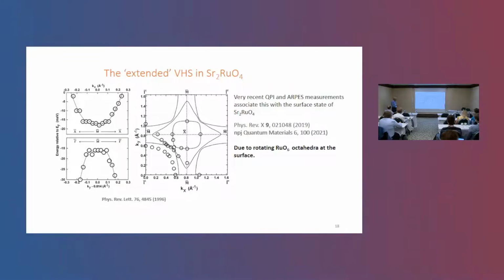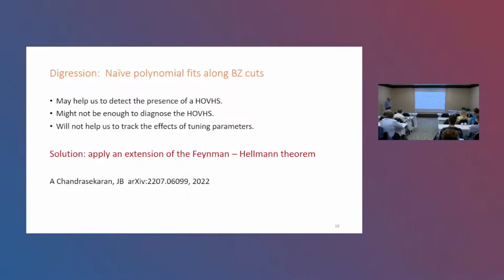People now, especially groups in St. Andrews, did two different classes of experiment, quasi-particle interference experiment and ARPES measurement, and understood that what is extended is a surface state of 214 due to rotating of the ruthenium oxygen 6 octahedra close to the surface. It is energetically favorable for these octahedra to rotate differently from the bulk, so you can observe this type of singularities.